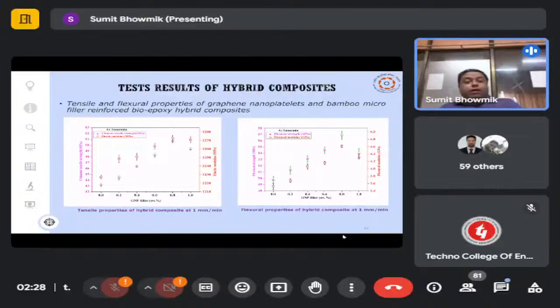Okay, so in that case also elastic modulus, ultimate tensile strength, flexural modulus and flexural strength also increase with bamboo. In case of bamboo, it has been observed that 0.8% graphene incorporation gives the best property. Whereas in case of jute, 0.4 to 0.6% graphene incorporation gives the best property, and in case of bamboo, it is at 0.8% graphene incorporation. But in all the cases, it is to be remembered that in bamboo and jute, the filler incorporation is 5%.